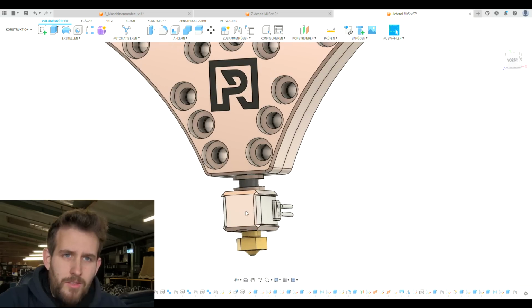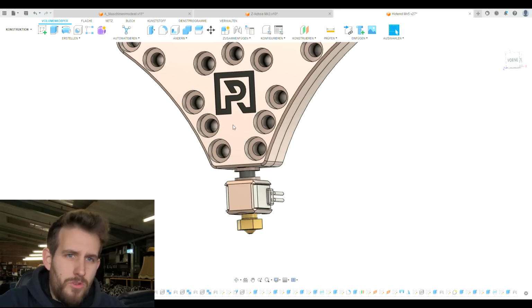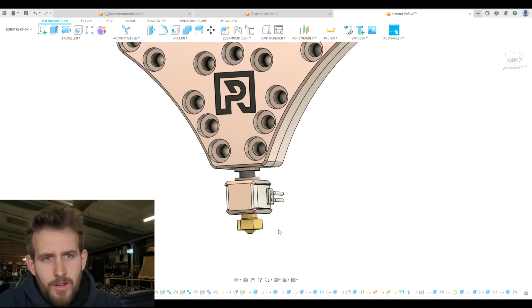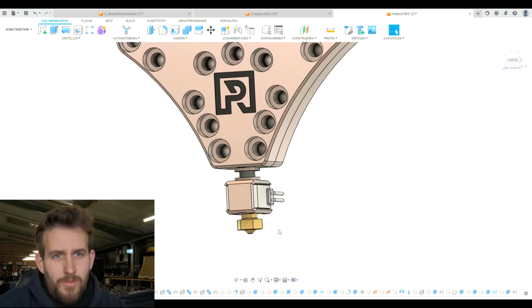Then the second heat zone is there to actually give this system a lot of control, because either way, whatever is coming out of the top part, we're going to use the tip heater to make it an even temperature, because if we have the capabilities to heat it up to 280 degrees, that helps our pressure and we can use it to melt the filament evenly. But every degree on top that we add to the filament, we have to cool down again, and that is not helping with our third main issue, the cooling situation.